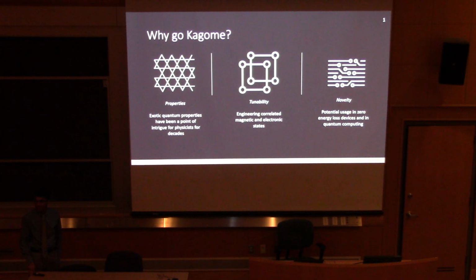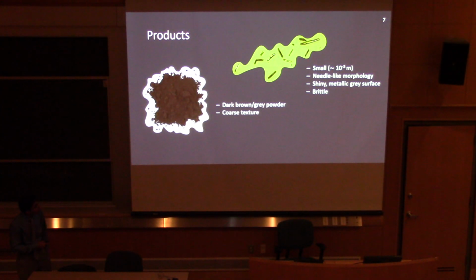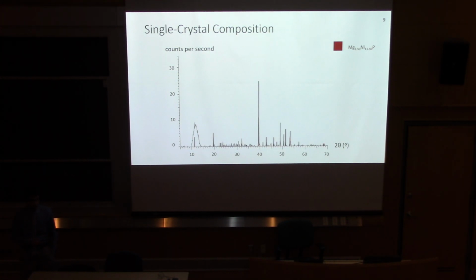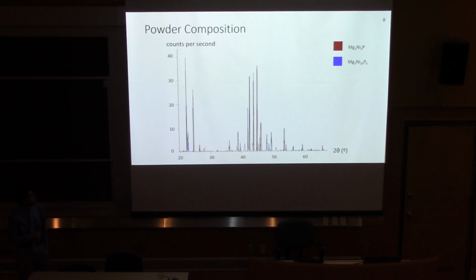Any other questions? Yes? So for these other stoichiometric compositions that you're getting, how do you know that those crystal structures aren't somewhat interesting? So actually, for this one, Hongyu suggested we just do some resistivity measurements for the sake of curiosity. Nothing interesting has been found. And for the nickel-rich phase, the literature has shown that heating for extended periods of time and cooling slowly results in magnesium losses and the formation of this nickel-rich phase. There have not been any studies so far to demonstrate any interesting facet of this, but that's also another open venue for study.